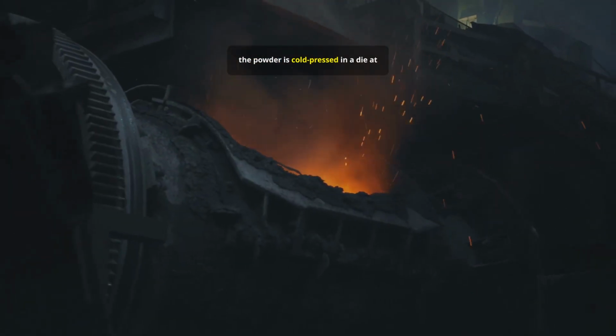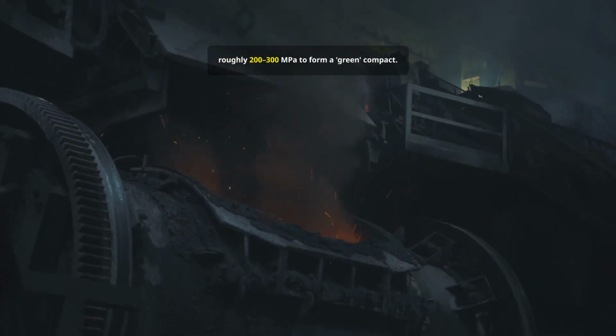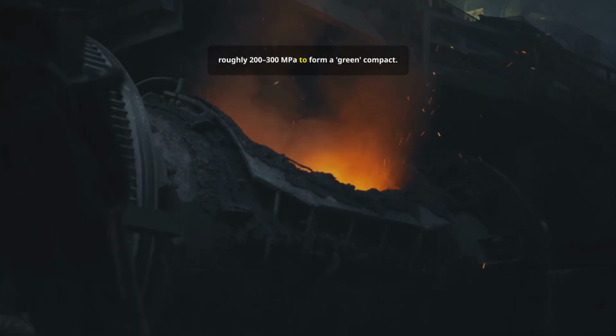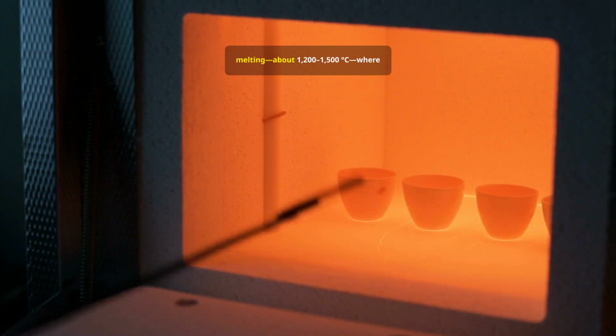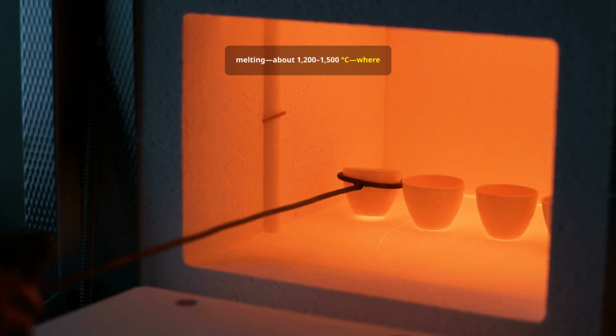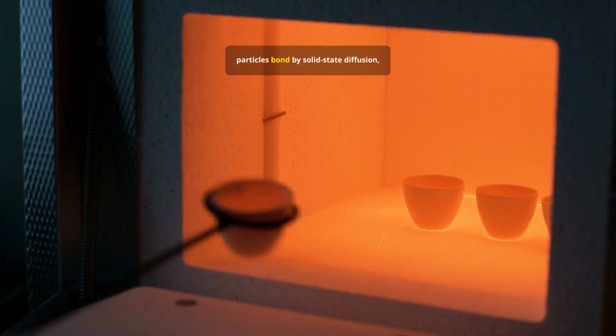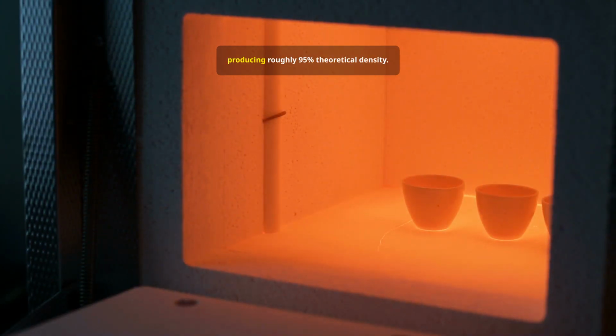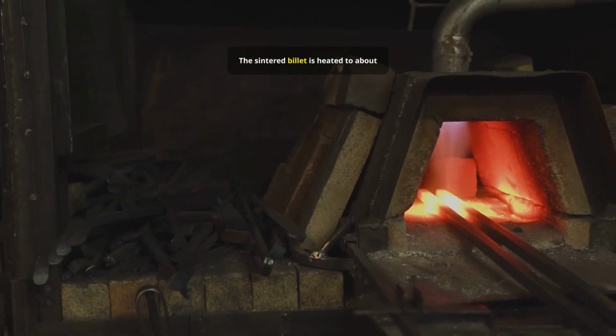First, the powder is cold-pressed in a die at roughly 200-300 MPa to form a green compact. Then it's sintered just below melting, about 1200-1500 degrees Celsius, where particles bond by solid-state diffusion, producing roughly 95% theoretical density. The sintered billet is heated to about